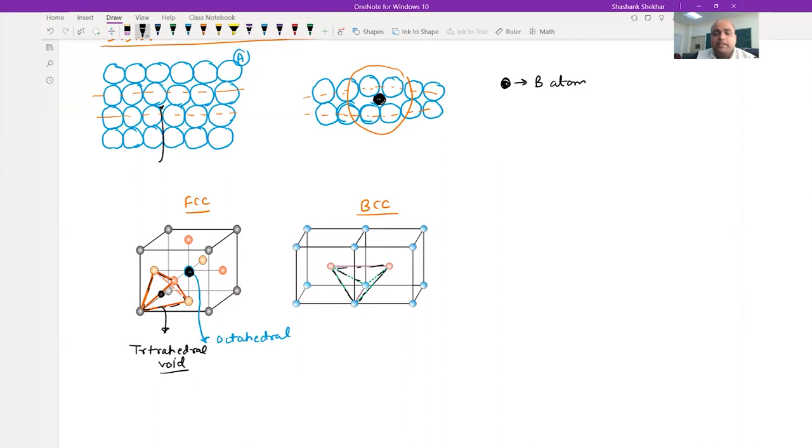So whether it is BCC or FCC, you are going to have some void, some interstitial positions. And the solute atoms are going to sit in those octahedral or tetrahedral voids. And since they are sitting in octahedral or tetrahedral voids, the distortion, what you see here on the top, this type of distortion is going to be non-symmetrical in nature. That means interstitial